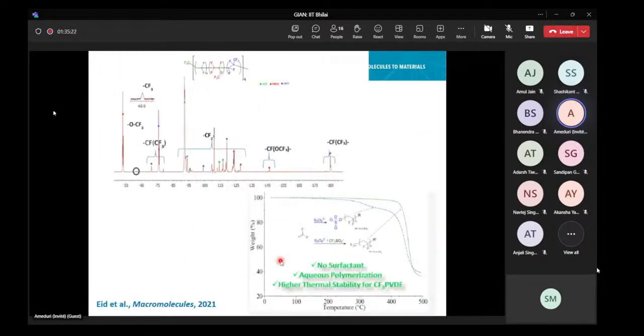If you look at the NMR, for us this is very important because we made so many models with a CF3, knowing that when you have a CF3 adjacent to a CH2 of VDF, you have a signal at -61. When we make an expansion of that, we see the quintet. And from the different characteristic signals, this is, for instance, the HFP from here. You also have a lot of signals here, but this one is linked to VDF.